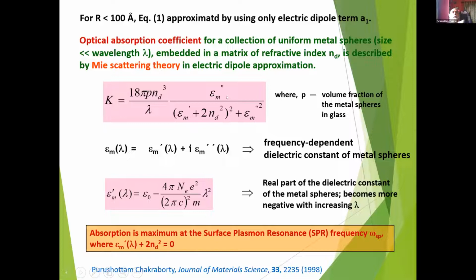This is 18 pi p nd cube, etc., where you can see epsilon m single prime and double prime. Epsilon m single prime is the real part of the dielectric constant of the metal particle, and epsilon m double prime is the imaginary part of the metal quantum particle in the glasses, and nd is of course the refractive index of the host.